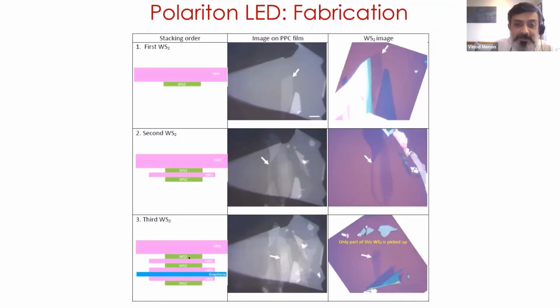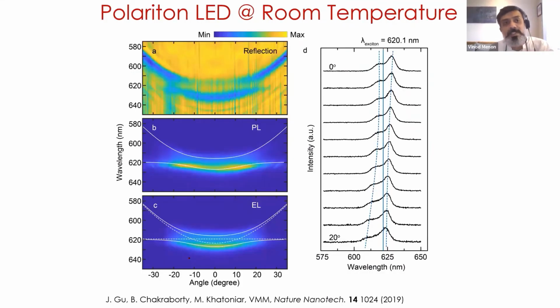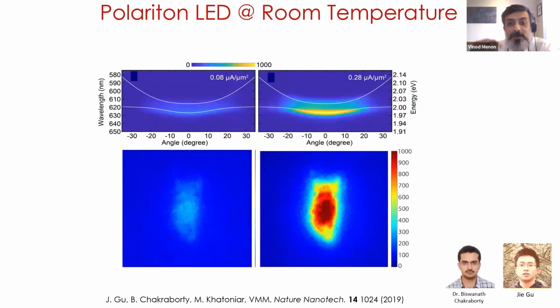So this entire device had about 11 layers inside it, and what we show here is that indeed you can show it to be strongly coupled in white light reflection and photoluminescence. But the thing that you want to pay attention to is the electroluminescence. You can electrically drive this device. It shows that it actually emits polaritons, and the polariton emission follows the dispersion that is expected from this device.